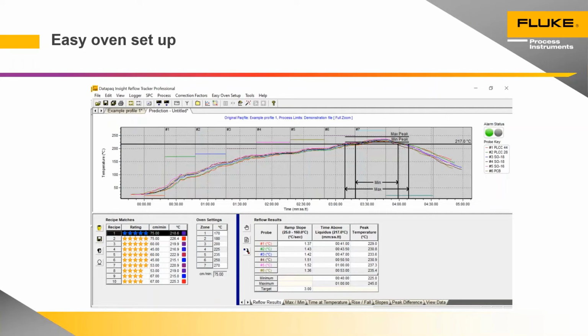But this is really to help out people that are having issues when changing or setting up an oven for the first time. Do that initial profile, tell it what you want to achieve, and the software's come back and predicted some settings here. Now, you will notice the first one at the top of the list is now very fast. It's 75 centimeters a minute as opposed to the 45 we were operating at. It does fall within specification. It would allow you to increase productivity.